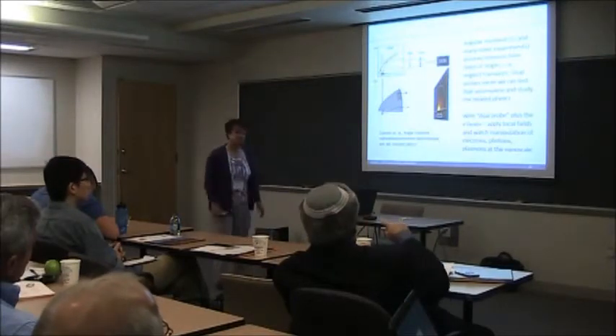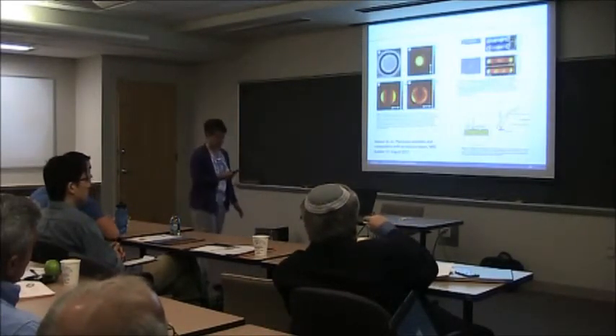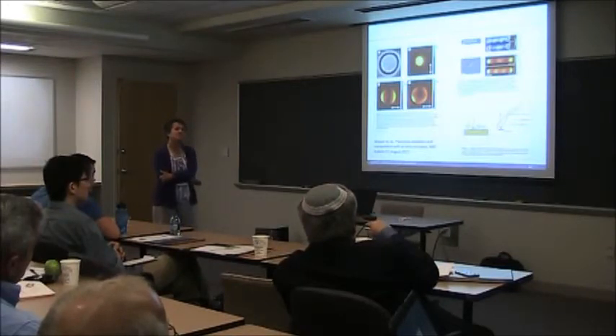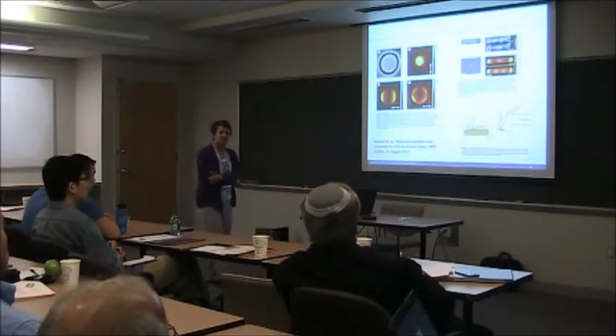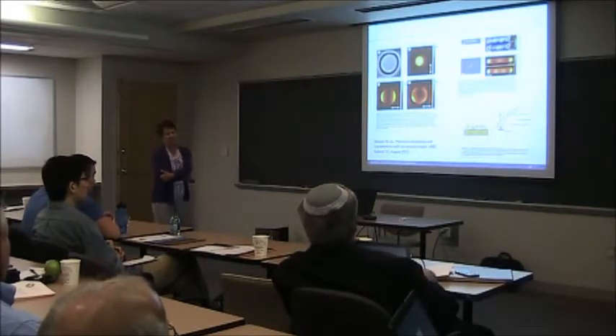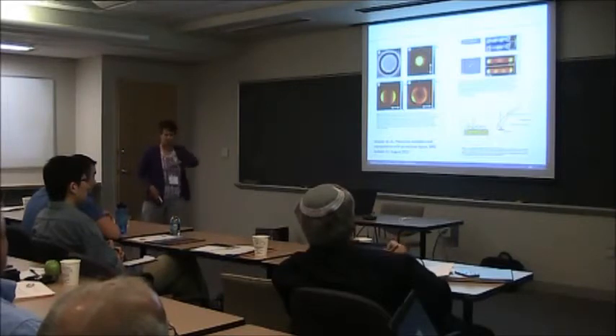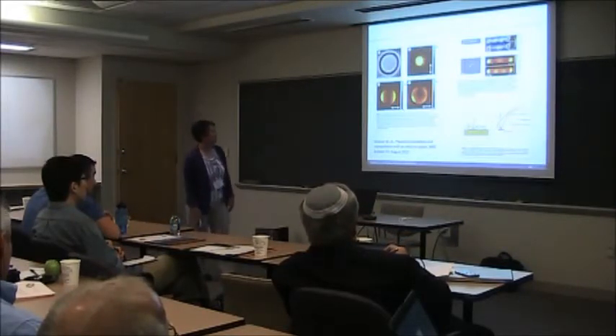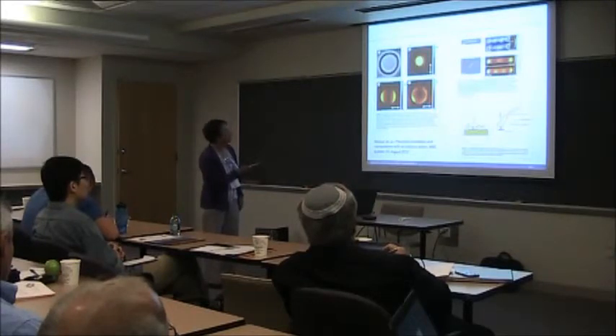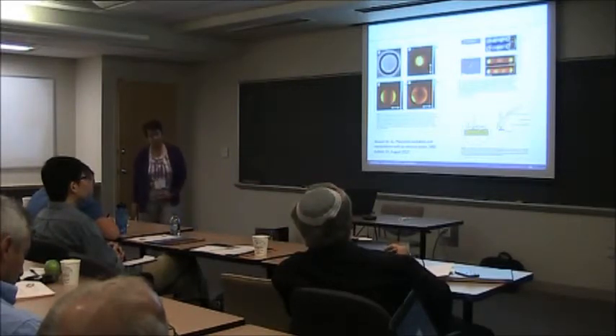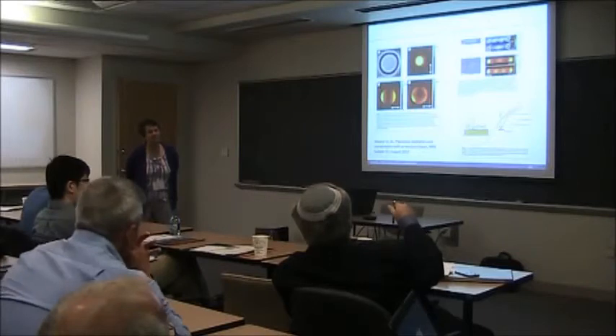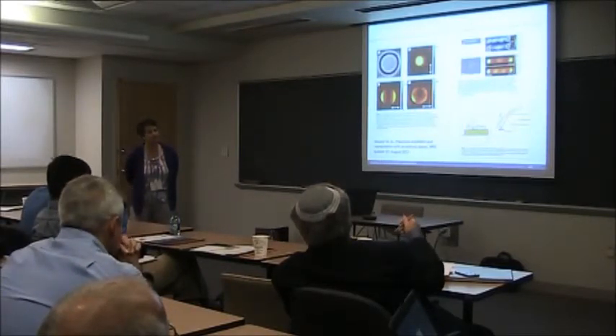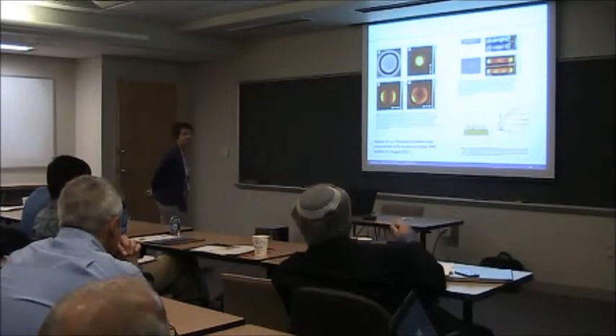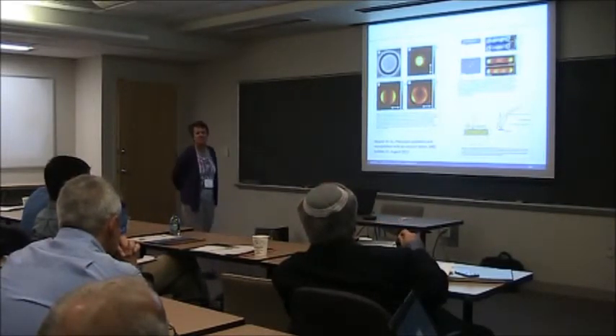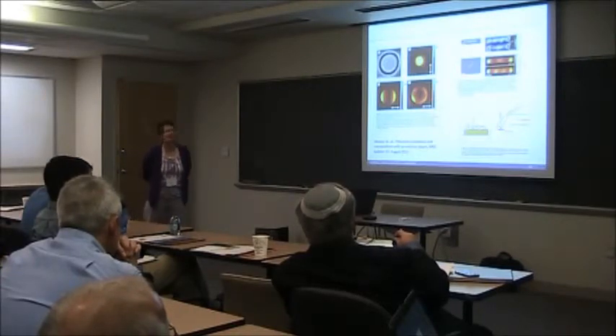In the plasmonic one that you just showed, this paper, this is nanometer with SEM. Right. This is cathodoluminescence. It's E-beam generated plasmon mapping. Yeah, that's right, with the beam scanning now. Right, absolutely, and polarization resolved CL detection. So in principle, you could, even close to a plasmonic structure, have an electron beam, because it has an E field, which could in fact generate plasmons. Yeah. Right. So we should be doing this. We need the right structure. But yeah, this could be very interesting.